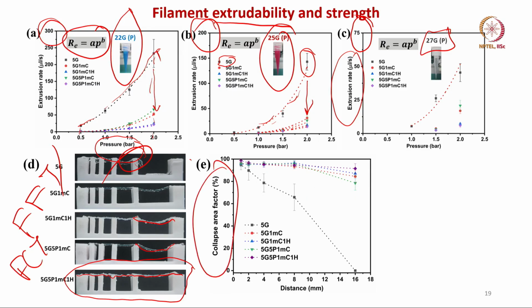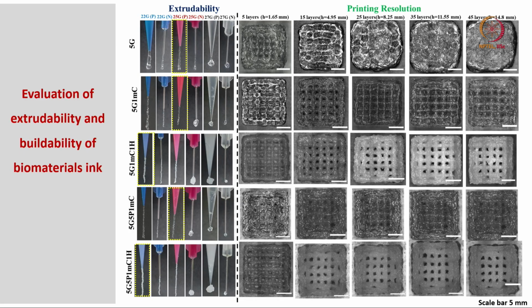And this is the collapse area factor with the distance. You can see that for all the other compositions it is close to 80 to 90%. Extrudability and buildability are the two major things that drive the different bioink compositions. So, when extrudability was measured, different sizes of nozzles, both plastic and metallic, were used for all the compositions. Now, the optimum one, which gives a very stable filament with relatively good strength, is 5% GelMA with 1% carboxymethyl cellulose.